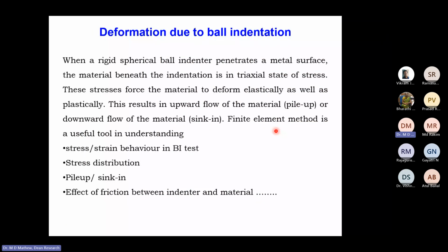Now, I should mention here that when a rigid spherical ball indenter is allowed to penetrate into a metal, then the material under the indenter will be in a triaxial state of stress. So the material immediately under the indenter will be subjected to both elastic and plastic deformation. So these stresses will force the material to deform elastically as well as plastically. So this can result in an upward flow of the material, which we call pile-up of material, or it can also lead to downward flow of the material, which we call sink-in. And here there's a lot of scope for doing finite element analysis of the material behavior under the indenter in order to evaluate stress strain behavior, stress distribution, pile-up, sink-in calculations, etc., etc.